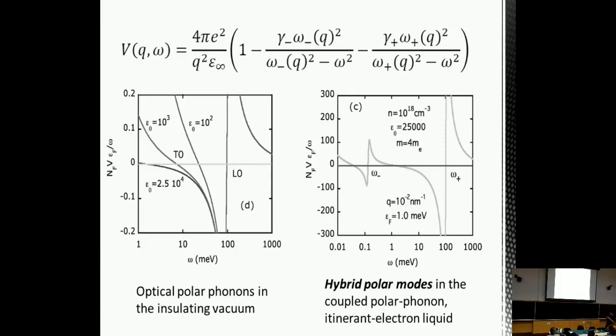So what you can notice here is that when we tune the system to a ferroelectric quantum critical point, you're actually tuning this intersection point here all the way to 0. It's easier to see in the low doping side. So when you tune the transverse optic mode frequency to 0, then you open up this large negative region of attraction for electrons down here. But the same here. These attractive parts of the function become much bigger as you go close to the ferroelectric quantum phase transition.